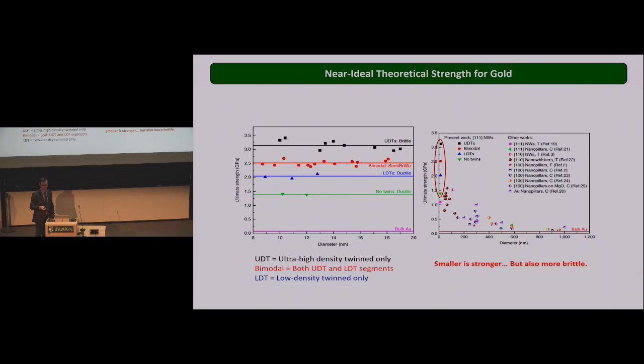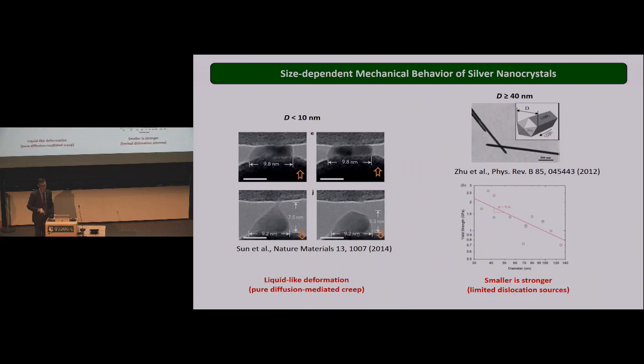And so in the last part of my presentation, I will go back to the silver nanowires. This is a more recent study we concluded this year that shows that these silver nanowires can actually achieve both ideal strength and very large ductility and superplasticity if you define their size properly. So here's the problem. In the case of silver nanowires, the literature is in good agreement and says that when your wire is more than 40 nanometers in diameter, it follows the same smaller is stronger trend, and the strength is very high. Okay, so we know that from both experiment and simulation.